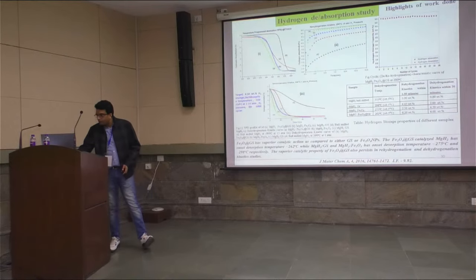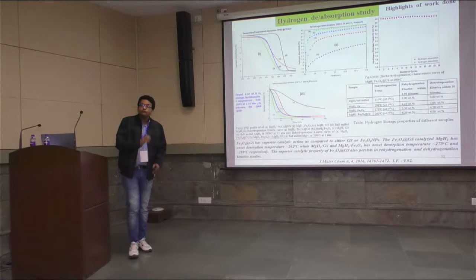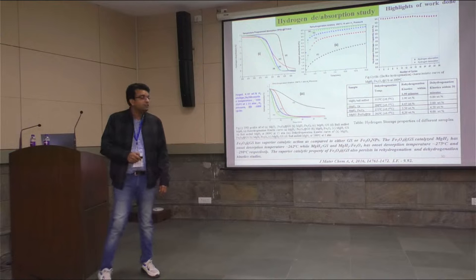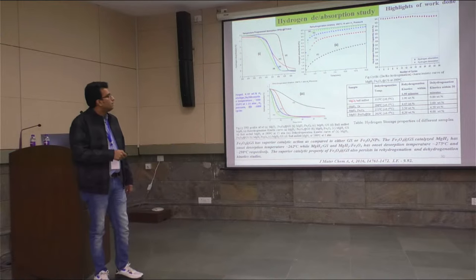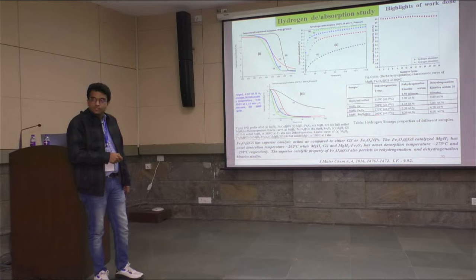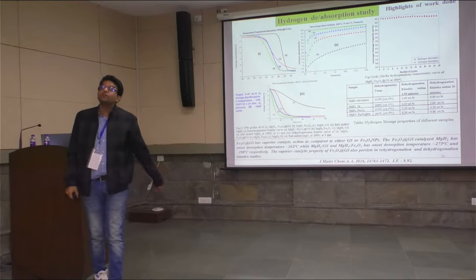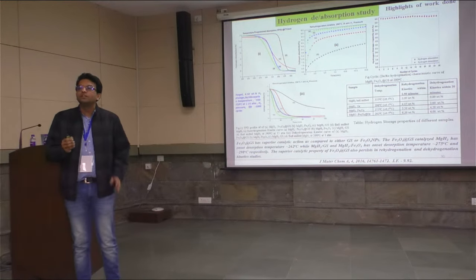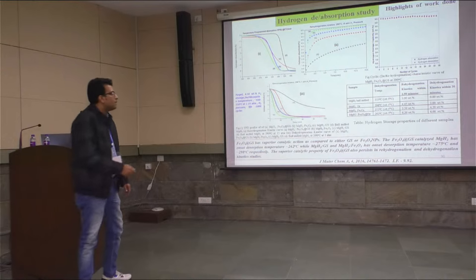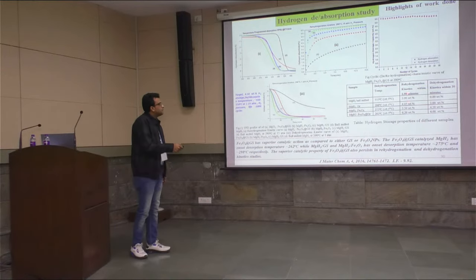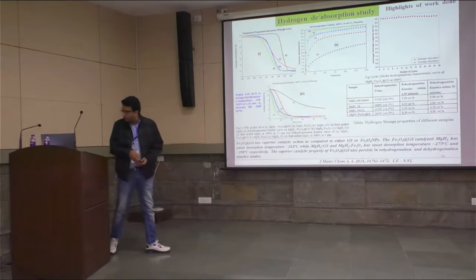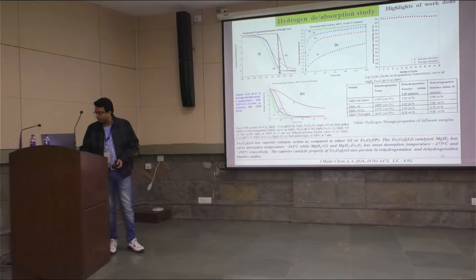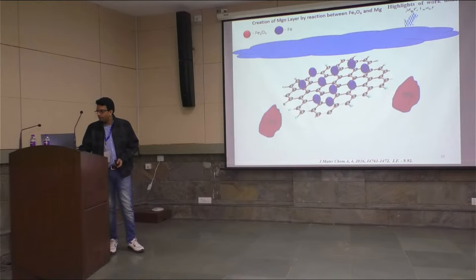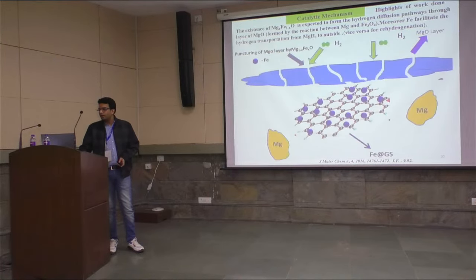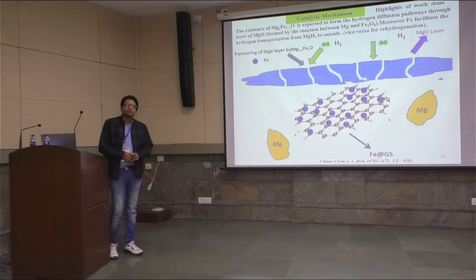And finally, what we have observed is that by using Fe3O4 on graphene as a catalyst, we are able to lower the desorption temperature of magnesium hydride from near about 350 to 260 degrees Celsius. But the target which I have shown you is around 100 to 150 degrees Celsius. So still we are way away from the target. And you can see there are capacity enhancements also if you use Fe3O4 on graphene as a catalyst. Now, these are the mechanisms that I have developed based on electron microscopy studies.